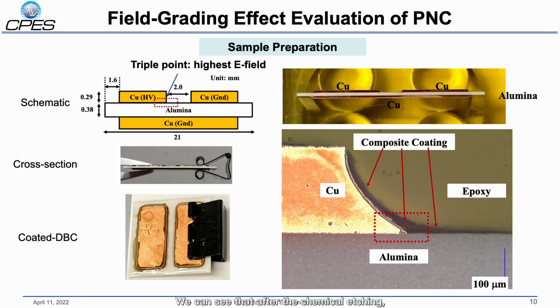We can see that after the chemical etching during the substrate preparation, there's a sharp corner left here, which could cause very high electric field intensity concentration here.